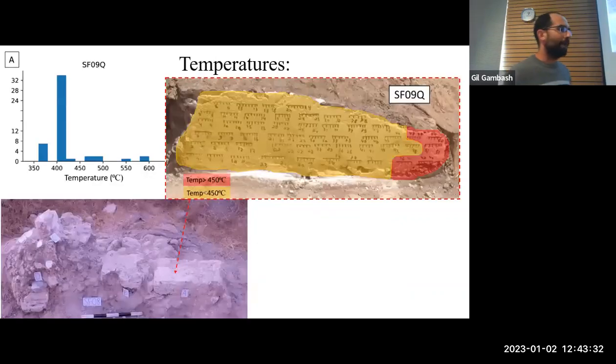Moving on to the temperature, all the material I sampled here gave us 600 degrees Celsius or more. So it's very high temperatures, everything originating from higher elevations, including this roof segment that was down below. Only these bricks that were down below, this one here that I cut in half, gave me less than 450 degrees Celsius, most of it, marked here in yellow. And only on the outer side of one side, we had more than 450 degrees Celsius. So this shows that this brick was actually, like all the others, heated in situ, but it wasn't heated to hot enough temperatures to make it really consolidated, but only to 450 degrees.